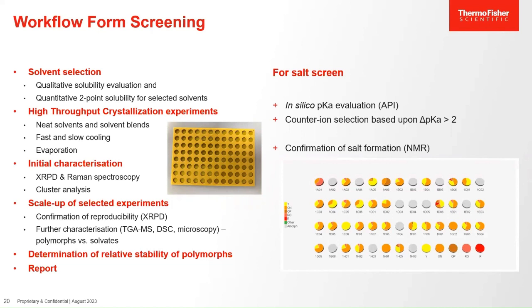And with the large amount of data that we're generating, we use cluster analysis to look for similarity in the diffraction patterns, group them, and then we will pick a certain number of promising experiments for scale-up experiments. Scale-up experiments are typically done at the 2 to 10 milliliter scale. They confirm reproducibility of the crystallization conditions.